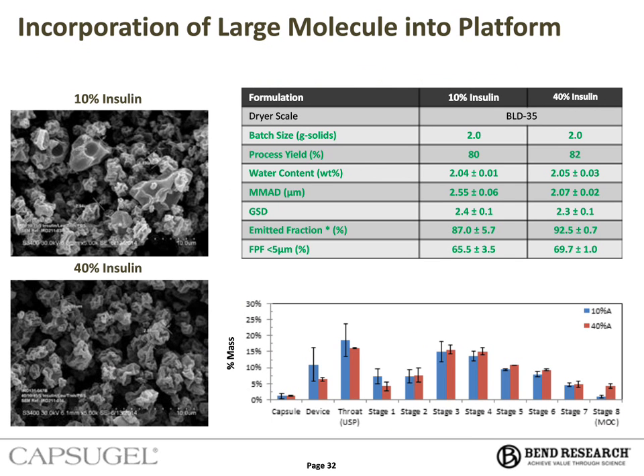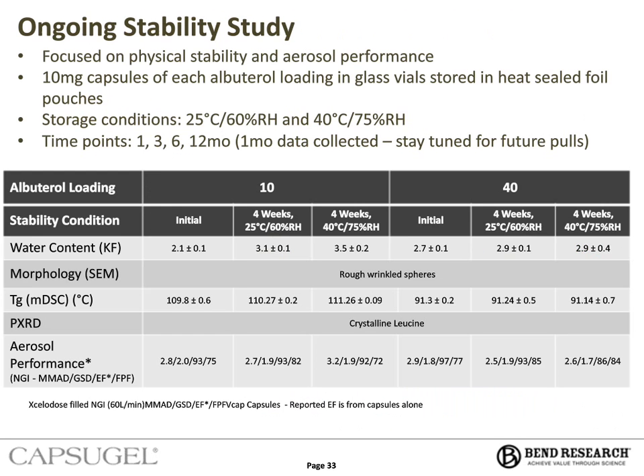So the last slide, as part of the case study, shows just how we've set up this study. So right now it's the 10 and 40% albuterol loadings with the focus on physical stability and aerosol performance, as this is a model compound. So these are 10 mg filled capsules of each albuterol loading in glass vials stored in heat-sealed foil pouches, 25 C 60% RH and 40 C 75% RH conditions, and we're planning on carrying this through a year. But at the moment, we only have the 1-month data.